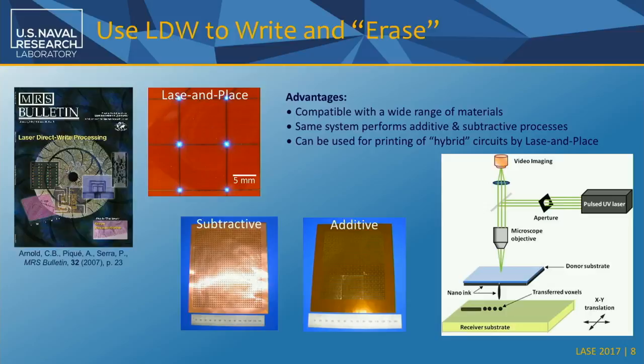You need to make a pocket to put a device in, to make a hybrid electronic? You can do that as well. Once you have that laser in place, all you need to do is adjust the intensity of the beam, the intensity of your pulse, and now you can go from a very gentle transfer, where you're not doing any heating or compromising the nature of the material, to ablation, where you can actually do micromachining.